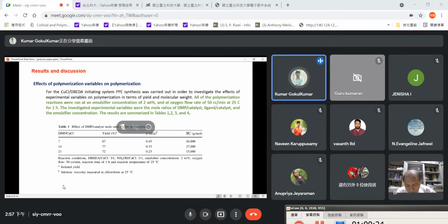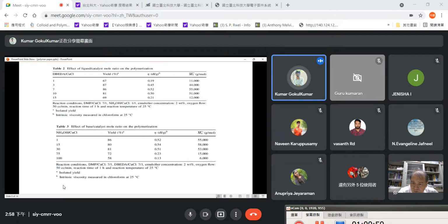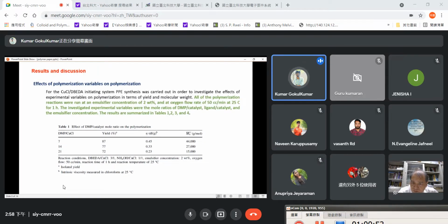This is the results and discussion part. All the polymerization reactions were run at an emulsifier concentration of 2 weight percent, and an oxygen flow rate of 50 cc at 25 degrees Celsius for 1 hour. In the experiments, the mole ratios of DMP, catalyst, and ligand catalyst, the emulsifier concentration, and the base catalyst were varied and are given in different tables. Table 1 shows the effect of the monomer to catalyst molar ratio on the polymerization.